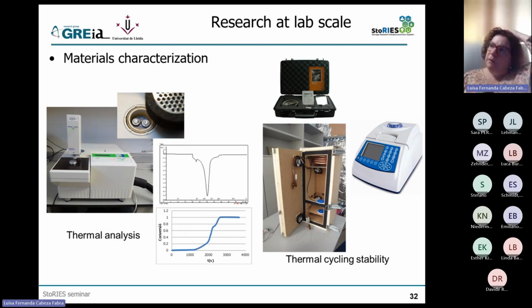And then when you are mixing PCMs with, for example, building materials like gypsum, concrete, it's very difficult to sample these milligrams of material and to ensure that you know exactly how much PCM is in there. So we wanted to go to bigger pieces of material to be characterized. And I'm doing this with my hands because this is more or less the size we were looking, 10 by 10 or 15 by 15 with 3 centimeters thickness too.